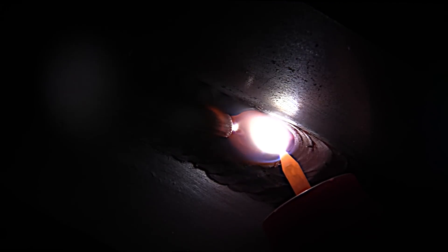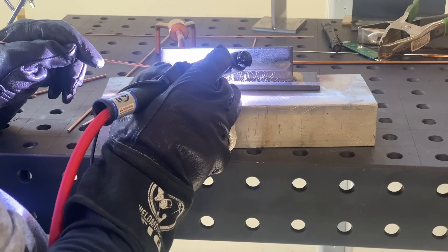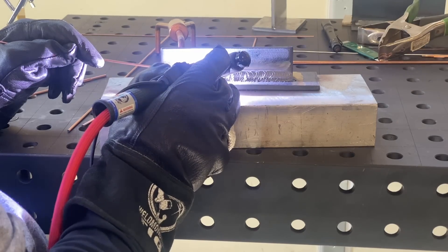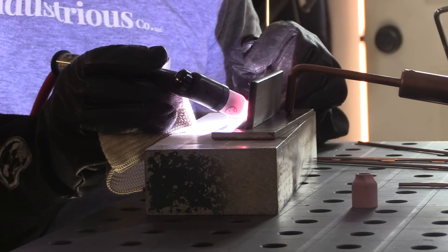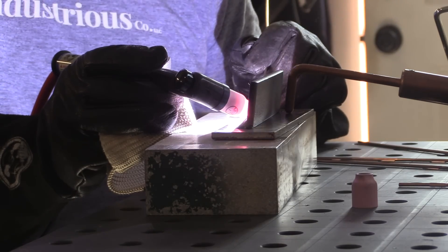It might have even been a good idea to drop down to a 3/32 size diameter filler metal for this last bead. It just didn't need much. What I'm trying to do here is angle the torch more in toward the top member and also really really watch the top edge of that bead and make sure to hold the toe for just a moment to avoid any undercut.